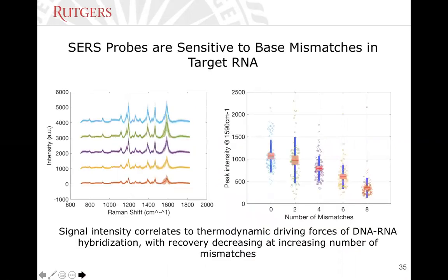What is also very interesting is that if we introduce on purpose mutations in the target, for instance, well, here, this is the target as it is in the virus. Here we introduce 2, 4, 6, 8 mismatches out of about 24 nucleotides, so about 30% of mismatches. We can see that we can not only identify them, but that the particles are still robust and they're able to identify the virus even if it has mutated, which is really, really relevant for the purpose of diagnosing the virus.